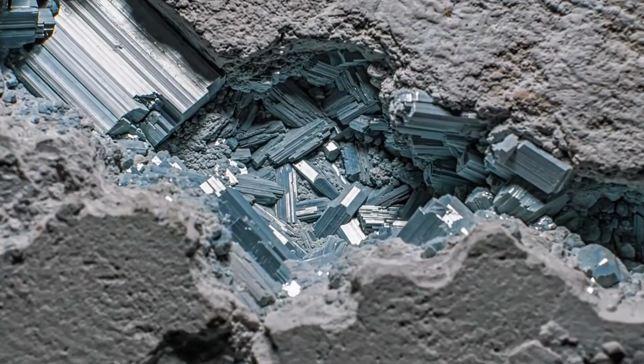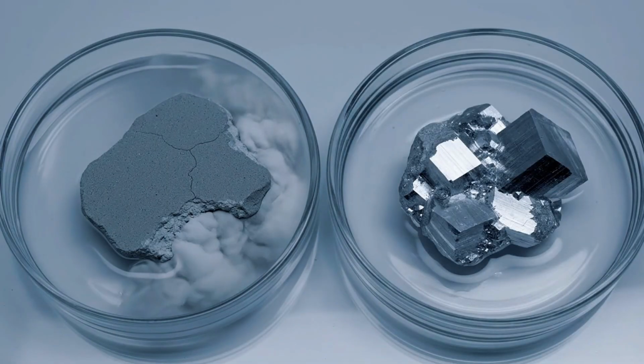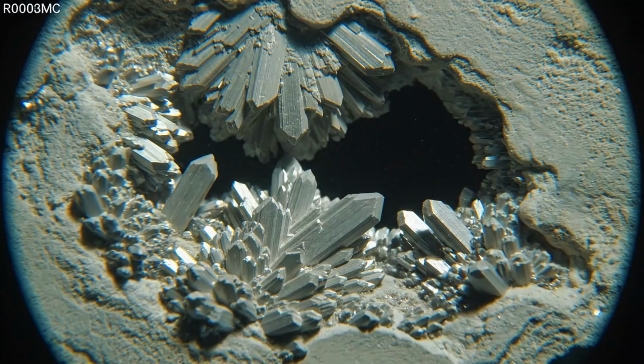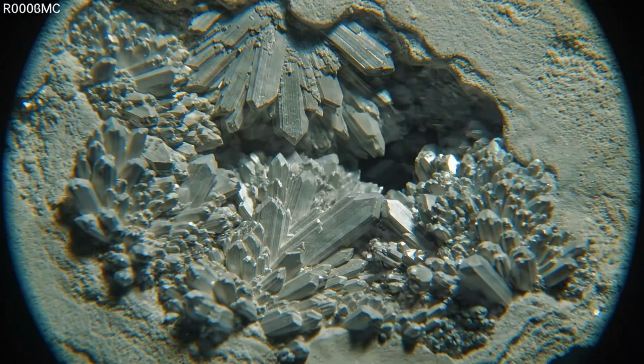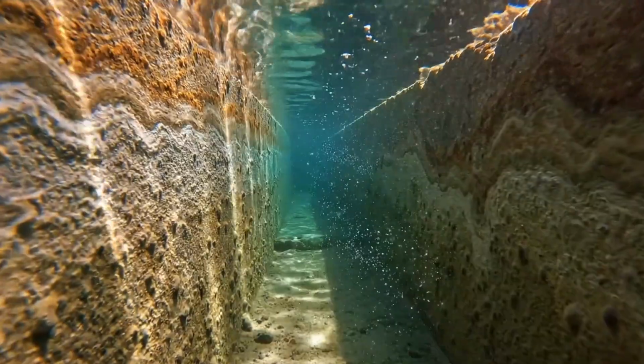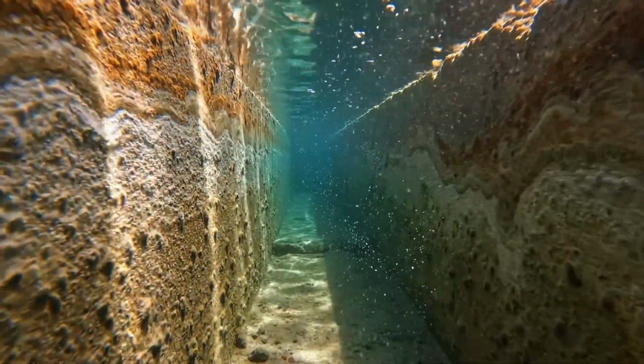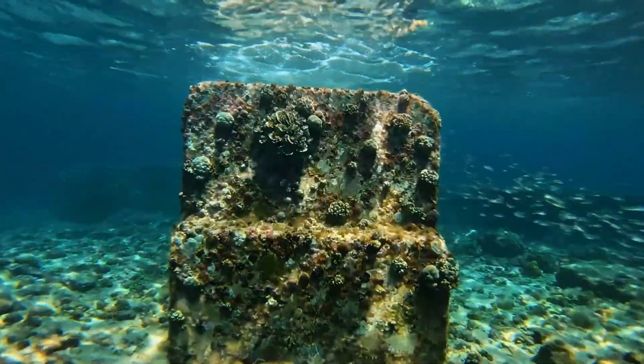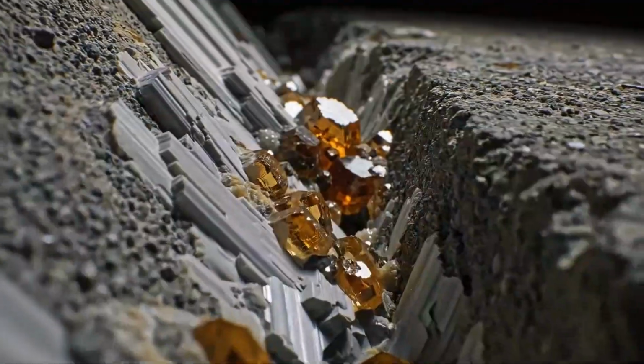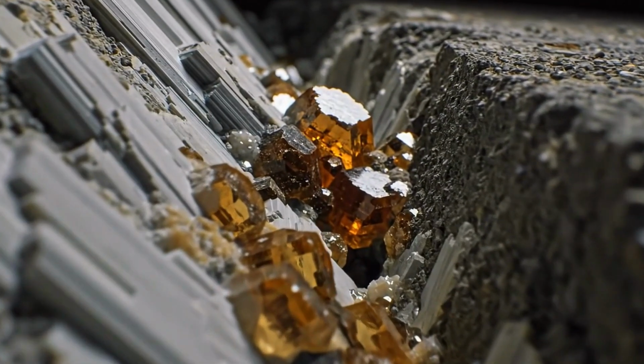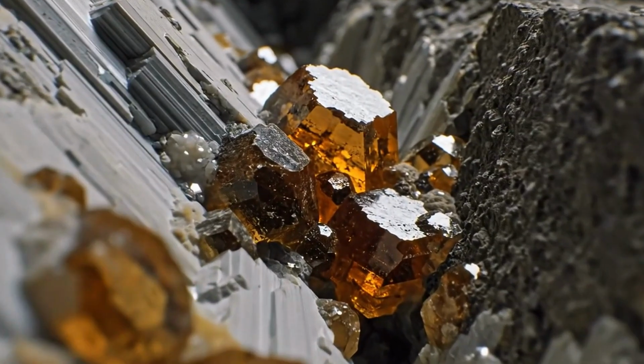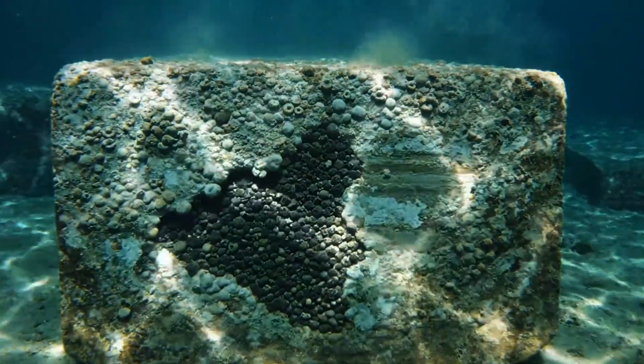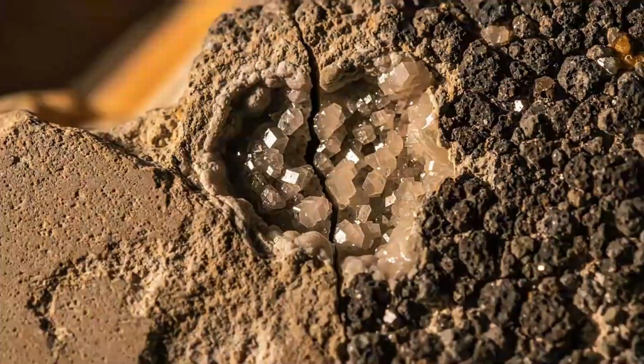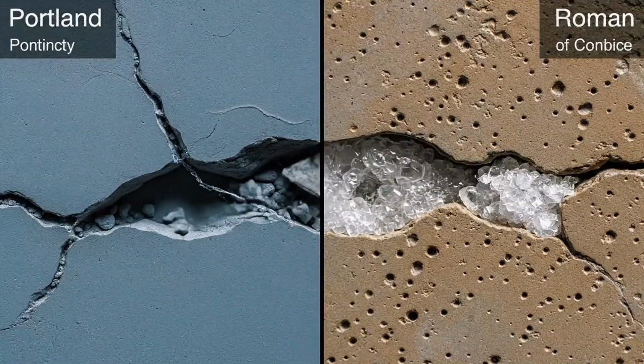Aluminous tobermorite is incredibly durable. It's resistant to chemical attack. It doesn't corrode. And critically, it grows over time. Here's where it gets remarkable. As seawater continues to permeate the concrete over decades and centuries, it doesn't degrade the structure. Instead, it triggers additional mineral growth. The volcanic ash particles continue reacting with the seawater, forming more aluminum tobermorite and another mineral called philipsite, both of which fill microcracks and reinforce the existing matrix. This is a self-healing process. Small cracks that would, in modern concrete, propagate and worsen, instead become sites for new mineral growth.